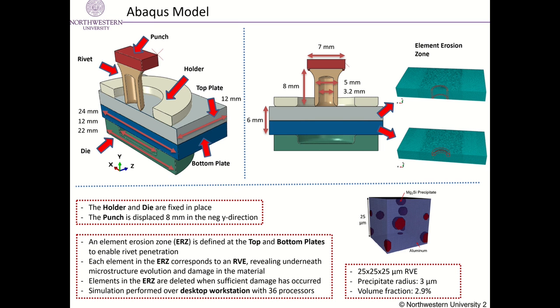The RVE replaces traditional material laws and provides detailed microstructure evolution. To allow the rivet to penetrate through the metal plates, element erosion is activated in the model. The element failure is predicted by the RVE calculation. Note that we designed the element erosion zone to minimize the mass loss when using element deletion. Only RVEs within the element erosion zone will compute microstructure damage and RVE failure.